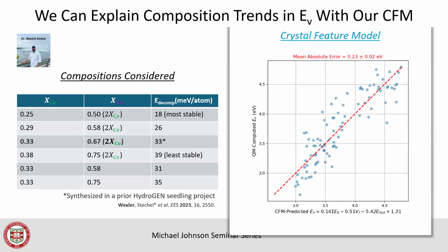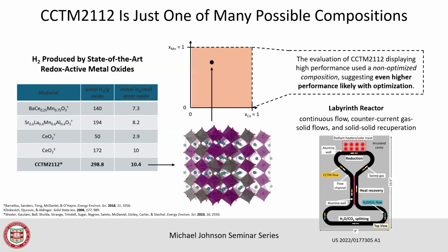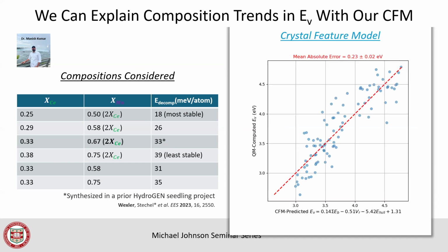Another thing that we can do is, because we can compute the energy required to remove these oxygen atoms from the crystal, we can do it for all these different compositions. We ended up generating a whole new data set. We used that linear model that I told you about, fit it, and what we found is this model works here as well. So what's great about that is we can do these 6 compositions, but then the infinity of compositions you can imagine in this square grid, we can just make a prediction using that model, which is like a snap of a finger. Whereas before, it would have required a lot of brutal quantum mechanics calculations. So that was a really important finding for us.